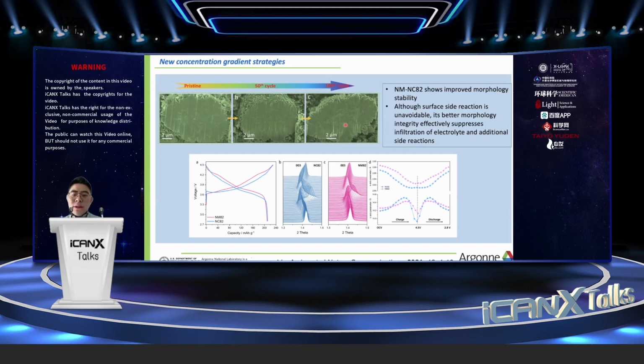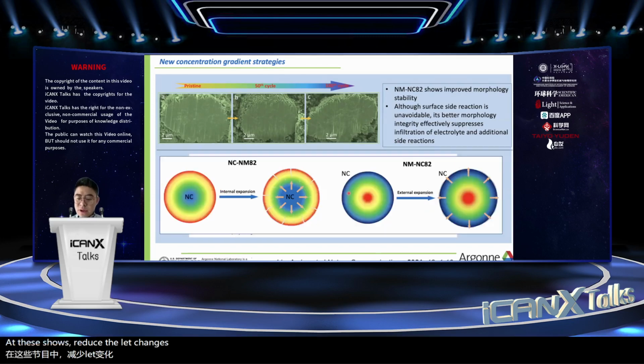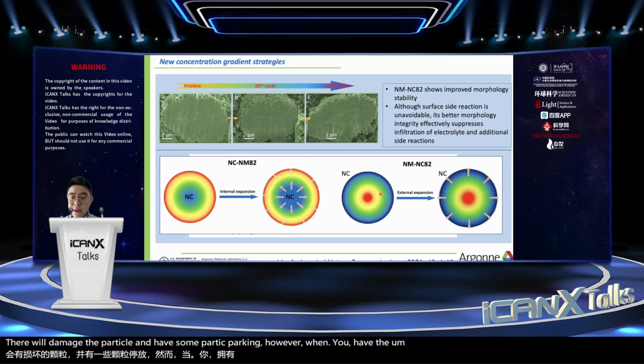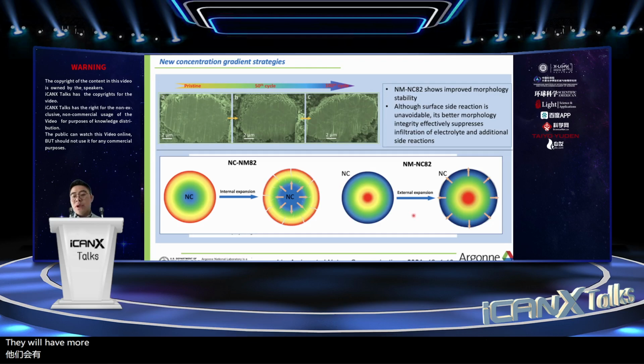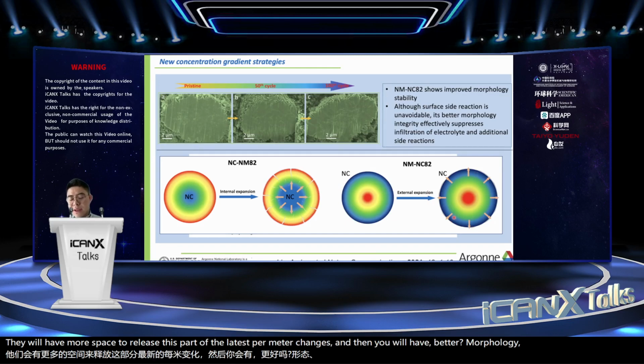So the reason why nickel manganese and nickel cobalt is much more stable than nickel cobalt manganese is this: nickel cobalt shows huge lattice parameter changes, and the nickel manganese shows reduced lattice parameter changes. When you combine these two together, and when you have NC-NM82, you will have huge lattice parameter changes inside the particle that will damage the particle and cause some particle cracking. However, when you have the nickel cobalt outside, they will have more space to release these lattice parameter changes, and then you will have better morphology stability, right?